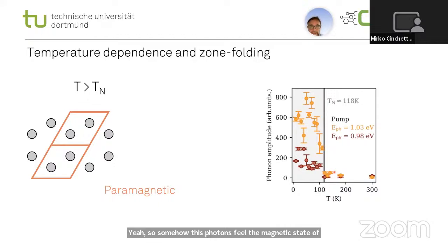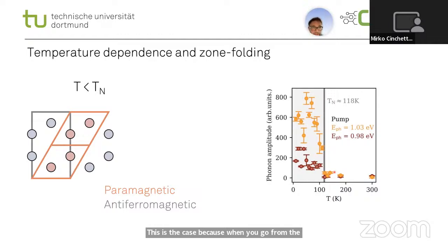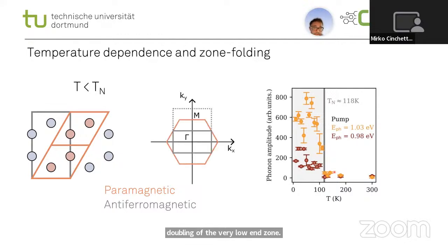And why is this the case? When you go from the paramagnetic to the antiferromagnetic phase, you have a doubling of the Brillouin zone. The M point of the paramagnetic phase collapses into the gamma point of the antiferromagnetic phase. This zone boundary mode then becomes optically active, as it is now in the center of the Brillouin zone. This is what is called a zone-folded phonon mode.